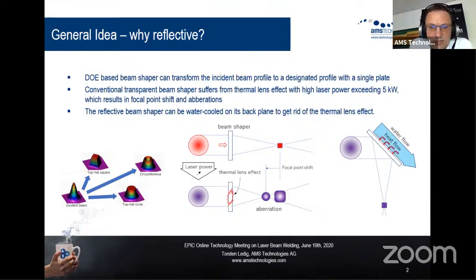In the different talks today, there was already some discussion on beam shaping and how you manage this. So the idea here is to change the beam shape by a reflective beam shaper, as you can see on the picture in the middle. Normally, by absorption, you get some heating in the transmissive beam shaper, leading to aberration and to focal point shift. So the idea, like here on the right picture, is that you have a reflective beam shaper, which can be water cooled on the backside of the device.